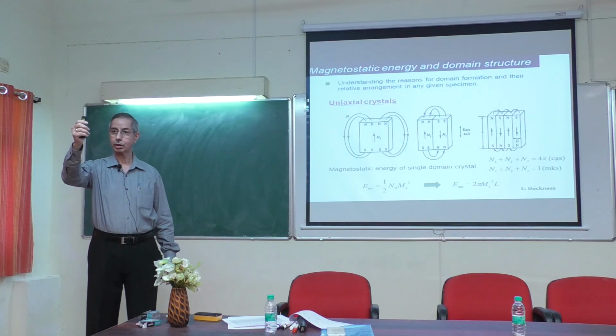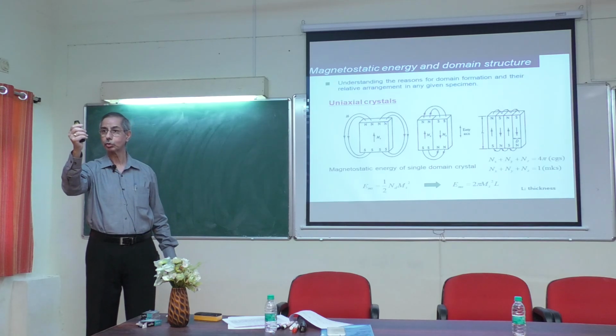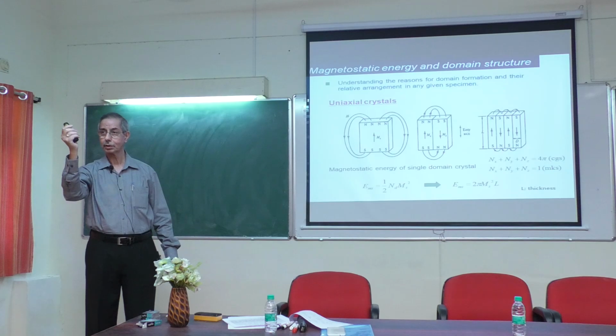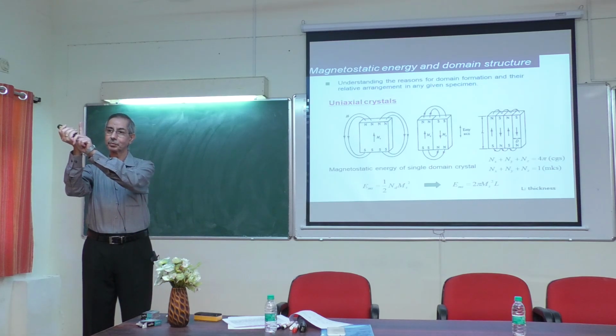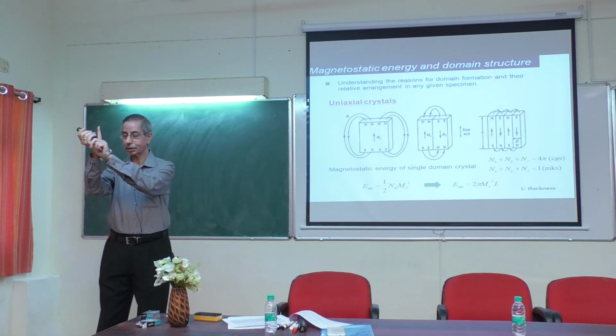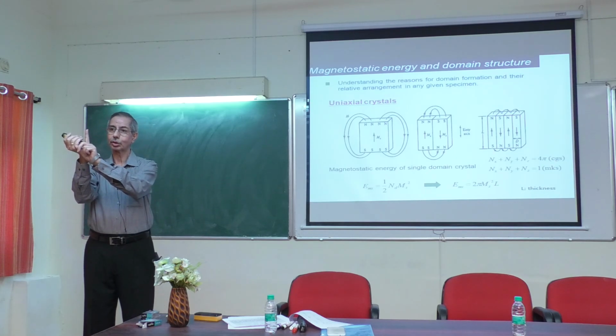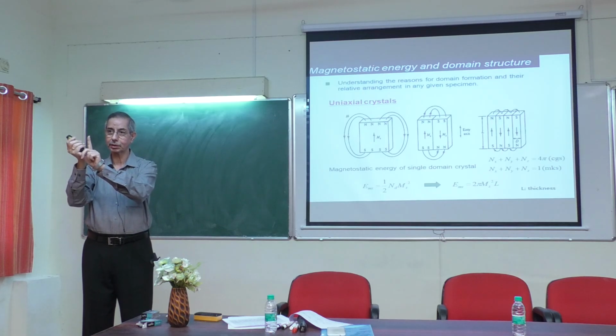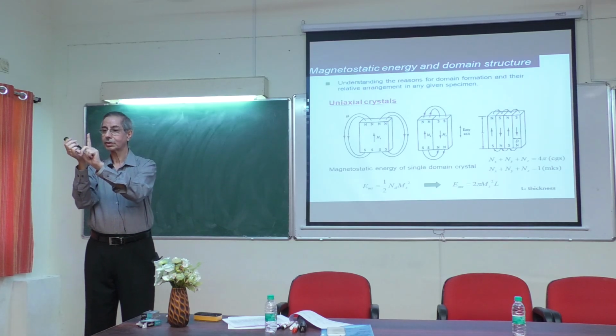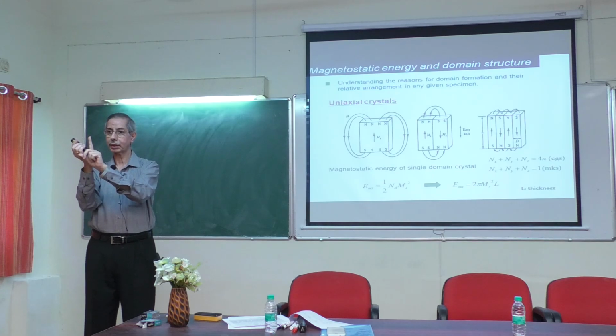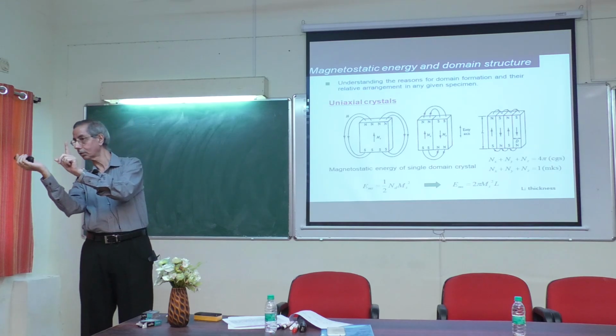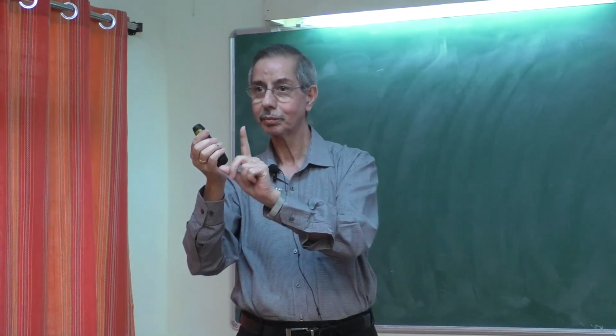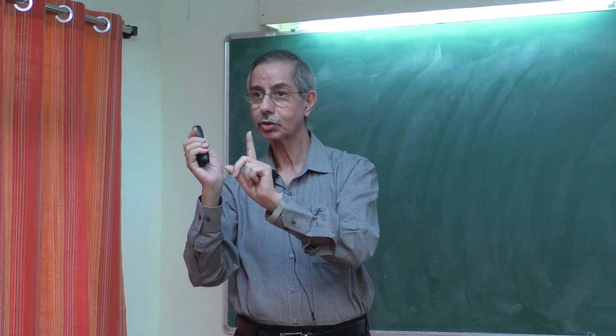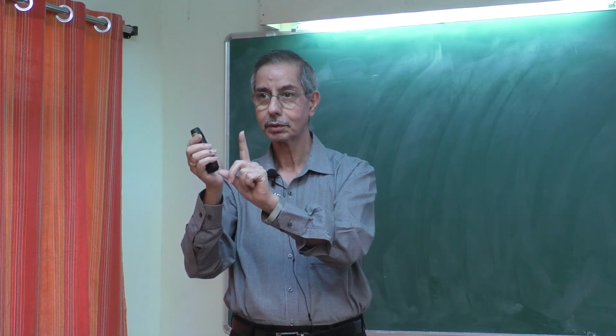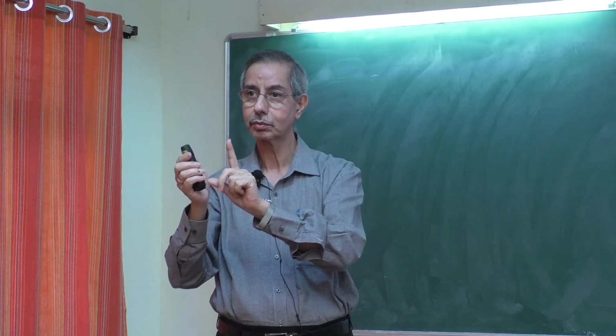So as the magnetization within the domain wall moves out of this direction, goes like this, this is the easy direction. First let us see the easy direction. So then there is an energy cost. That means there will be a slight increase in the anisotropy energy, right? At the same time, now the angle between the successive spins is not 0. It's a finite angle, because this one spin goes like this, and another one is going further, tilting. So this angle is not 0, it's some finite value, maybe small but finite. So there is some exchange cost of energy, right?